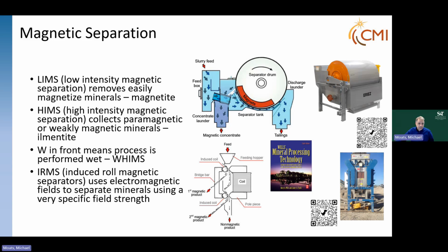We then go to this magnetic separation where we remove the magnetic materials. We can either use a low intensity magnetic separation to remove easily magnetized materials like magnetite. Then we can use a high intensity magnetic separation to collect paramagnetic materials, so this would be like ilmenite. We can do this dry or we can do this wet. If you're going into this research and you see a W in front of it, that just means it's wet. So this would be a wet high intensity magnetic separation.